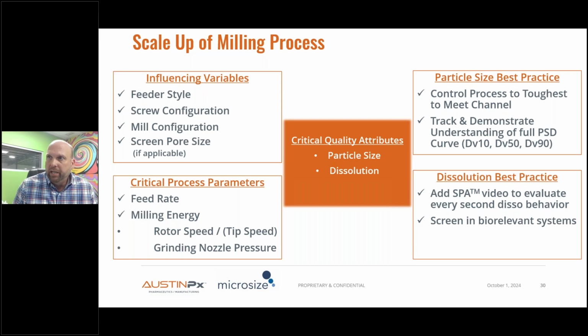So the CQAs in a milling process that we're trying to control and keep constant are the particle size distribution that's wanted, and then that leads to the dissolution that's present. So what we have found in any scale up factor is to definitely understand the entire PSD curve and be tracking all points, namely the bottom side and the top side, the D10 and D90, and the median D50. And so when we develop a process, depending on the distribution that we're talking about, we tend to develop that process and control it to the most difficult to control channel, and the others will fall in line. So if oversize is the issue, or large particles is the CQA issue that we're trying to control, then we'll control to a D90, but still track a DV50 and a DV10 to understand what those are.